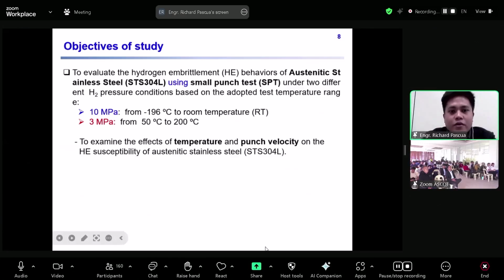That's why the main goal of this study is to evaluate the hydrogen embrittlement behavior of austenitic stainless steel using a simple method, which is the small punch test, using two different hydrogen pressures based on the temperature conditions, in which 10 megapascal was used for lower temperature and cryogenic temperature, and 3 megapascal for elevated temperature. In addition, we also aim to examine how the material behaves at different deformation rates under hydrogen environment, or different punch velocity, corresponding to the different temperature conditions.